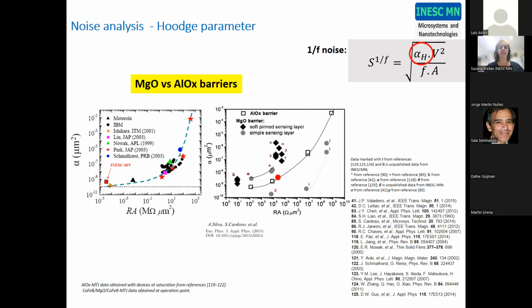So at the end, if we change geometry, materials, and whatever we want to change, the comparable factor between everybody in the world happens to be the Hooge parameter, at least in a certain community. So here we have been comparing, and we are adding up a lot of points in these curves, where we want to have a low resistance device, and we know that this reduces the Hooge parameter, but also we want to have small area devices, and we want to reduce the Hooge parameter.